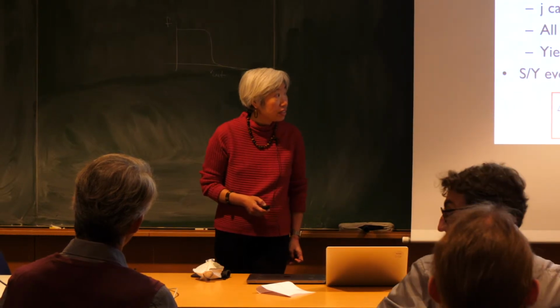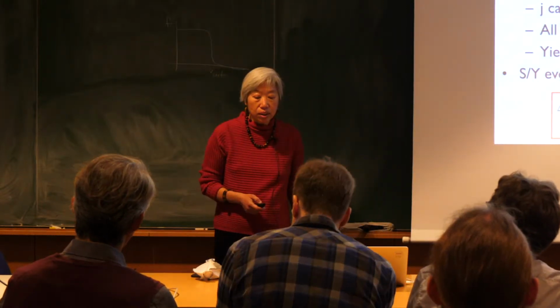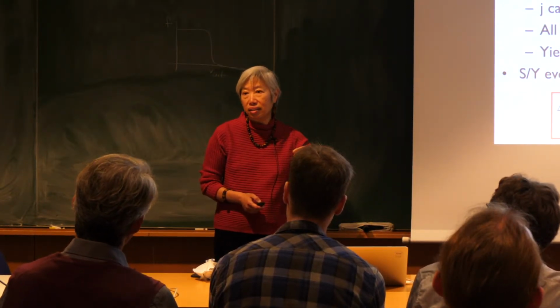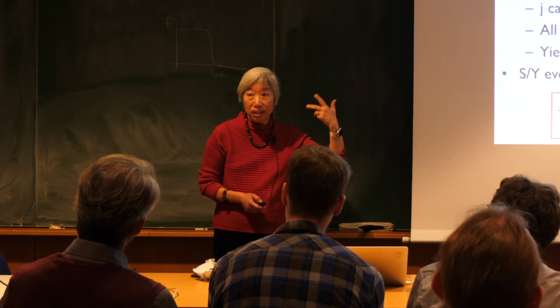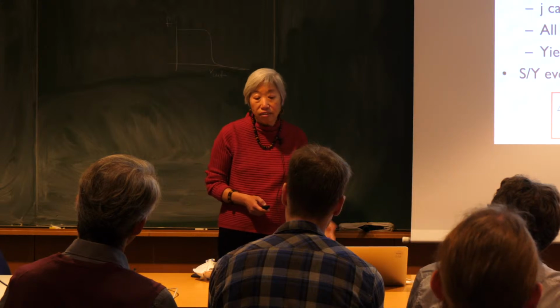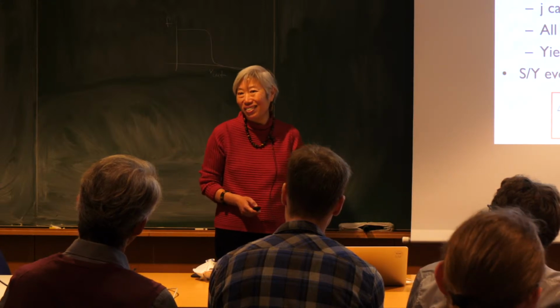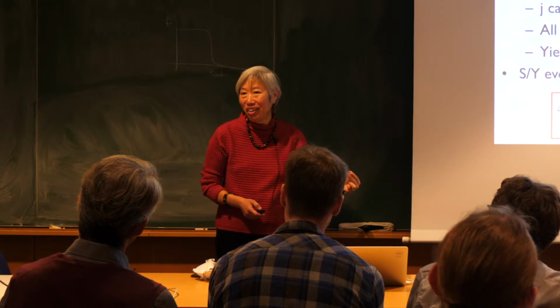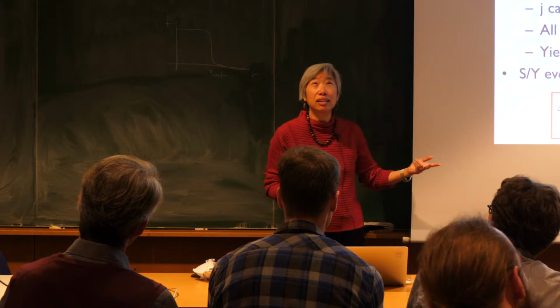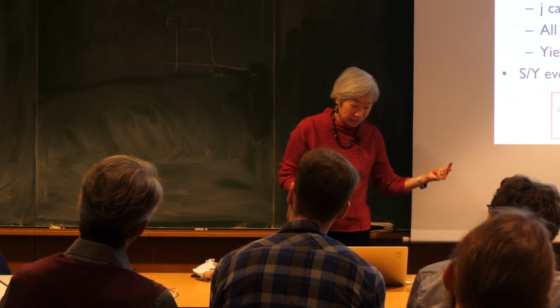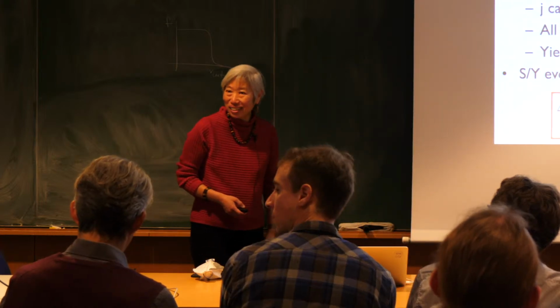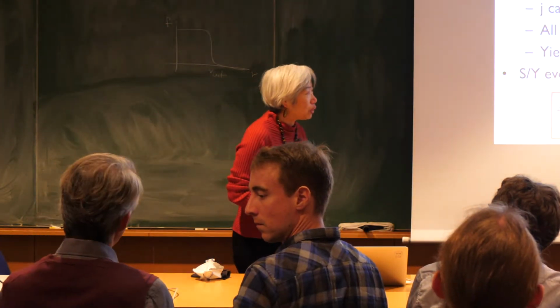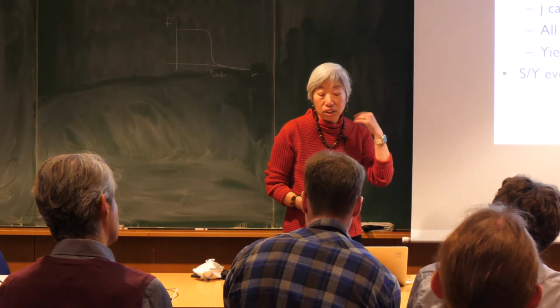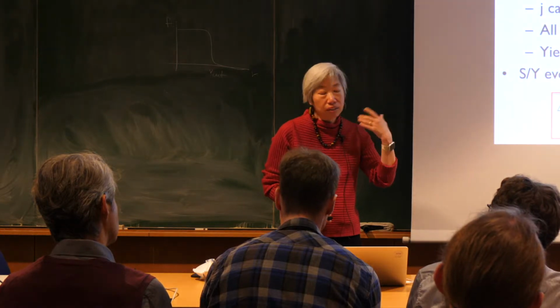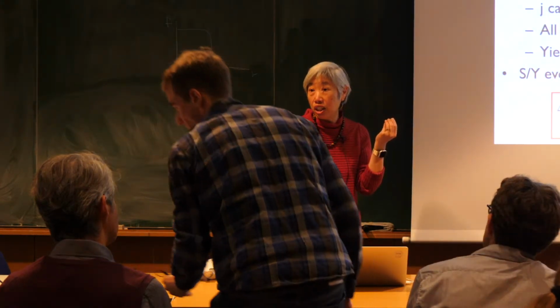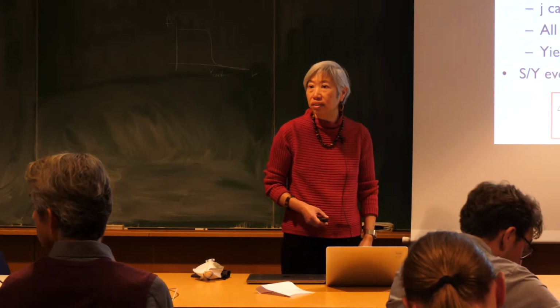Yeah. What we have found is that the weights are highest for the peaks and valleys of G of R. And for the first peak and then the first valley, they're the strongest. And in fact, you can capture most of the prediction accuracy of softness simply from the height of the first peak and the first valley. That actually captures something like 82% of the rearrangements. So it's actually quite good. And softer particles have lower peaks and higher valleys. So we view softness as simply a quantification of the cage. It's just telling you how strong it is. Yeah.